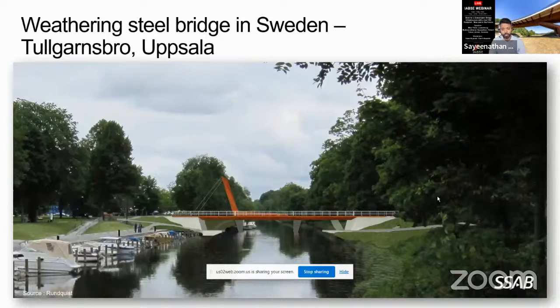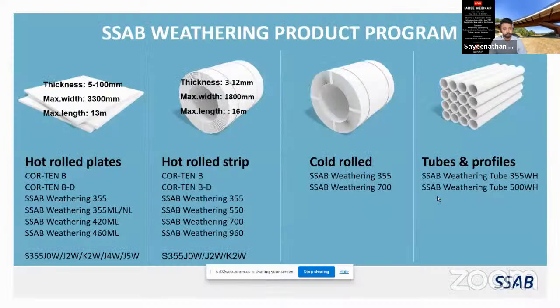And also when you use weathering steel over a water body and when you don't repaint, there is no risk of covering the bridge, and the water is not polluted by the paint or the paint debris. And we have quite a wide product portfolio in weathering steel, starting from hot rolled plates up to 460 megapascals. Then we also have it in hot rolled strip and cold rolled, as well as in tubular and profiles as well.